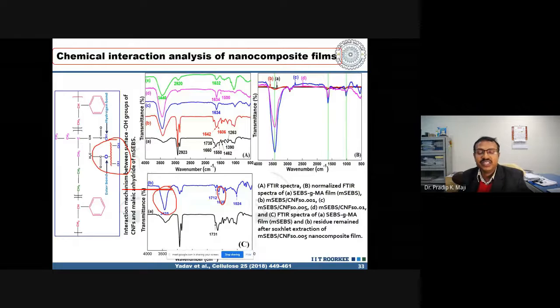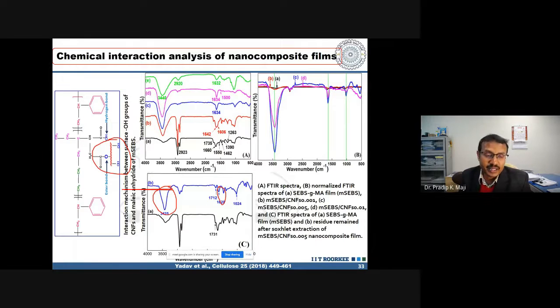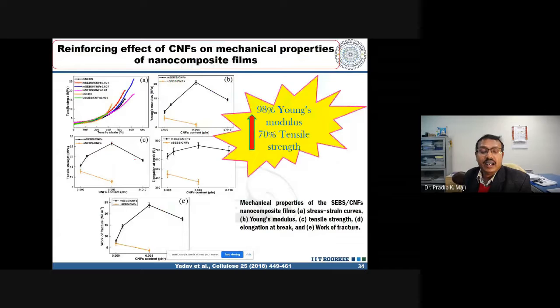Inseparable. That's why if I compare this phenomenon with that of bound rubber: like with any carbon black material, the carbon black will not be able to separate out from the rubber if it is reinforced. The higher the amount of reinforcing material, the higher the bound rubber property will be. Here, a similar thing happens, as in the residue itself there is polymer, and definite reinforcement has been happening that way. So this is how we have proved there is interaction.